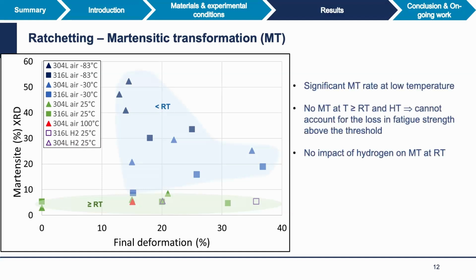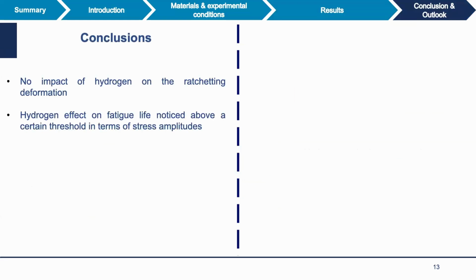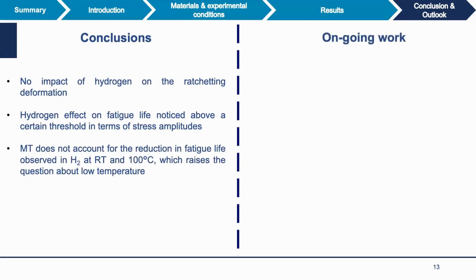And the point is that, as expected, at room temperature and 100 degrees C, we have no variation of the martensite during the fatigue test. That means at the end, we have the same amount. Of course, at low temperature, especially in the 304L, we have a significant increase in the martensite fraction. But it seems that this cannot account for the loss of fatigue strength observed at different temperatures.